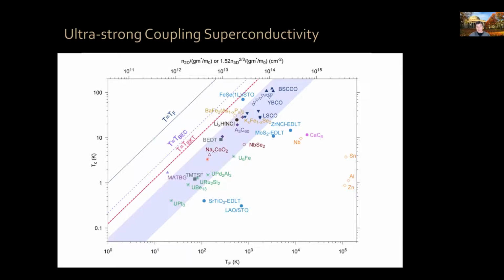Now, magic angle twisted bilayer graphene and magic angle twisted tri-layer graphene, depending on whether you take the 50% normal state resistance or the Berezinskii-Kosterlitz-Thouless transition temperature, they correspond to these data points here, okay? So as you can see, they are among the strongest, actually the strongest coupled superconductors that exist, okay? Only recently another superconductor, lithium zirconium nitride chloride, from Walsh's group, has demonstrated also this limit of ultra strong coupling.